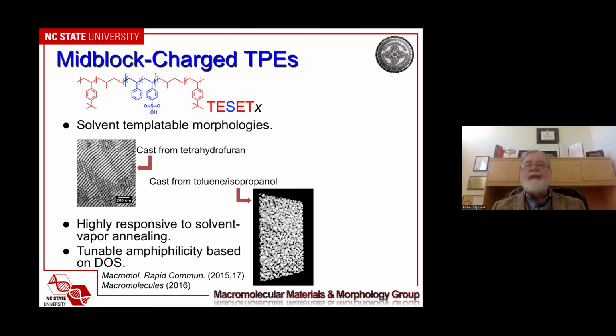So I'm going to switch over to a different type of material. This is an anionic polymer, and to be more specific, it's an anionic block polymer. So just to make sure that we're all on the same page, the block polymer has contiguous sequences along the polymer backbone. These are very discrete so that we can impart the functionality of those sequences into the polymer. So the end blocks that you see here are T-butylstyrene, denoted as T over here, and they are glass-forming blocks. So this provides the material with strength.